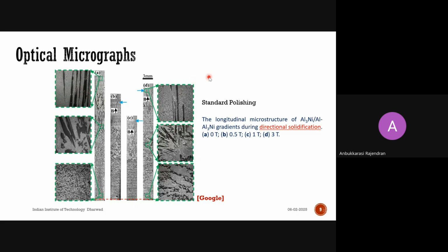So as I mentioned, sample preparation is important. After the fine polishing, some samples require one more additional procedure that is called etching. Some features do not require the etching process. Some features like precipitates or the cast structure, the dendrites with more alloying elements, may not require the additional procedure called etching. Etching is mainly helpful to reveal the grain boundaries. So you need not go for etching for all the samples. At the same time, not all samples can be analyzed in the as-polished condition either.